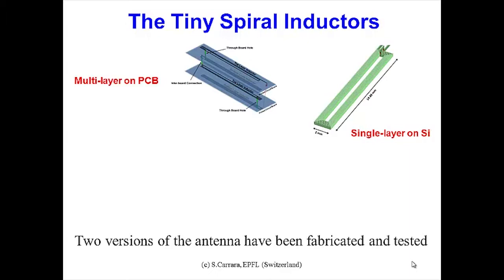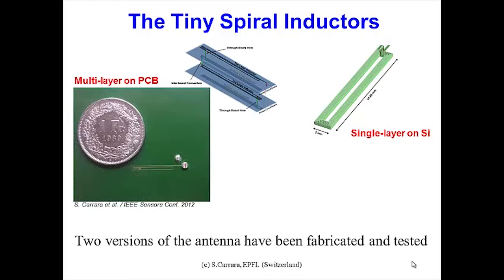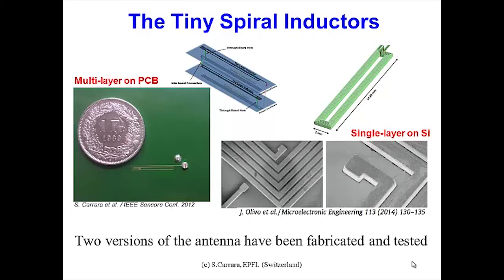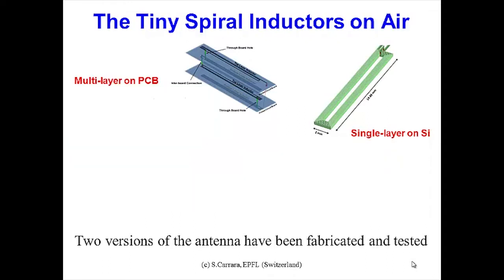So at the end, we ran for single-layer antennas, while it was really easy to obtain a multi-layer with the PCB state-of-the-art technology. This is just one of the first images from the top of a multi-layer copper antenna realized on flexible PCB, and this is indeed one scanning electron micrograph of the realized antenna on silicon.